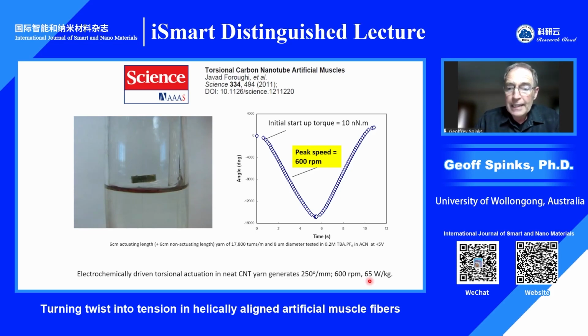Well, another key finding from this study was just why this is occurring. And what we discovered was that the electrochemical charging in the liquid electrolyte caused a swelling of the carbon nanotube yarn. The carbon nanotube yarn is quite porous, and during charging, ion and solvent is brought into the pores, causes the yarn to swell a little bit, and that swelling then causes this untwist. Discharging, the volume decreases, and the yarn can retwist. So that's why it's reversible.